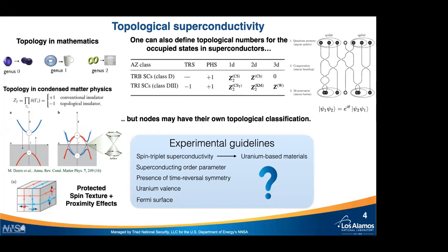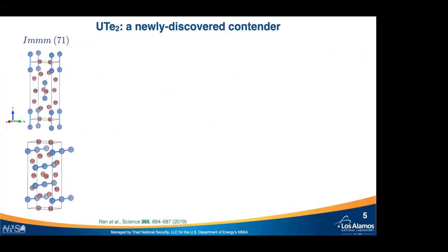But again, we are at the very base of the materials pyramid, and we need to take a step back and understand the candidate materials. So let me tell you about one newly discovered contender. That's uranium ditelluride, UTe2. It crystallizes in this complicated crystal structure, and when I say complicated, it's because it's orthorhombic, which you will see in a minute complicates things a little bit. But it has a very interesting crystal structure in the sense that you can see that along the a-axis, there are chains of uranium, and along the c-axis, there are ladders or dimers that stagger along the c-axis.